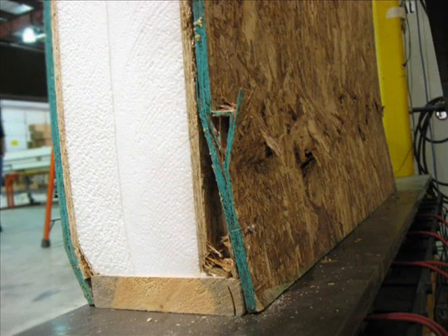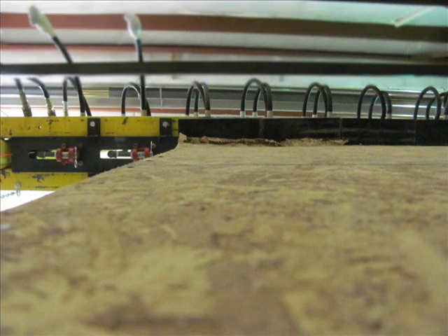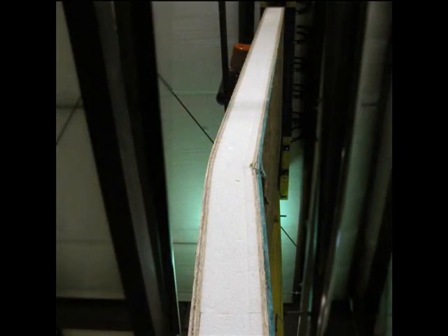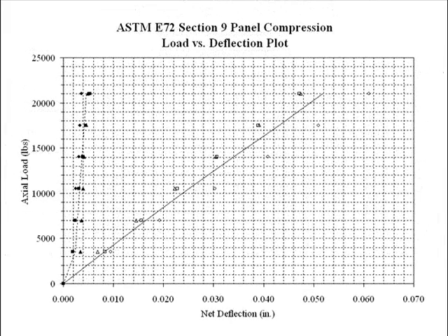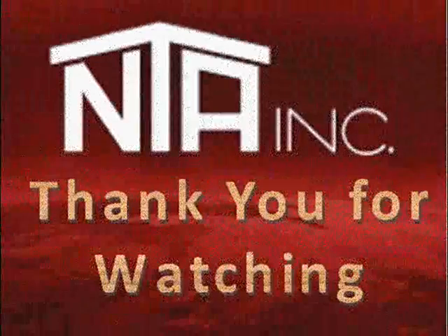Aside from reporting details on the materials and construction of the specimens tested and the equipment used, the report must include the maximum load achieved for each specimen, the gauge length for all deflection measurements, and test results in a graphical form, plotting the incremental loads versus both the shortening and bending of the specimen at each of these loads.